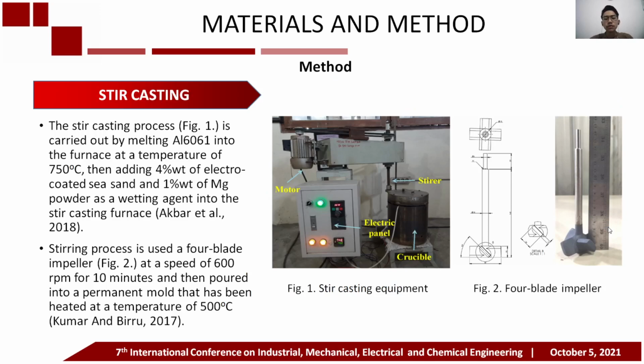The method used in this research is stir casting. The stir casting process is carried out by melting Al6061 in the furnace at a temperature of 750 degrees Celsius. Then, adding 4% wt of electro-coated sea sand and 1% wt of Mg powder as a wetting agent into the stir casting furnace. The stirring process uses a 4-blade impeller at a speed of 600 rpm for 10 minutes and then poured into a permanent mold that has been heated at a temperature of 500 degrees Celsius.